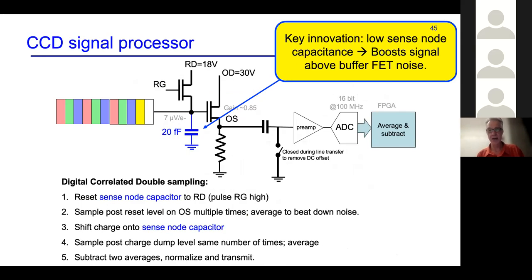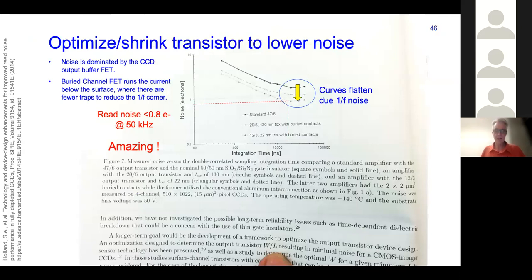The other thing, though, that's magic about a CCD is that this charge transport allows you to move the charge onto an extremely small capacitor. And so if the capacitor is small, the voltage which is induced per electron is comparatively large, with the result that we're able to boost the signal above the noise of these output transistors. And this is the magic that gives a CCD very low read noise. And the trick, of course, is that we need to optimize the geometry of those transistors as best we can in order to reduce the read noise.